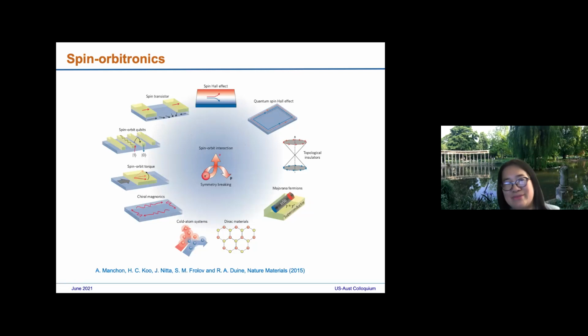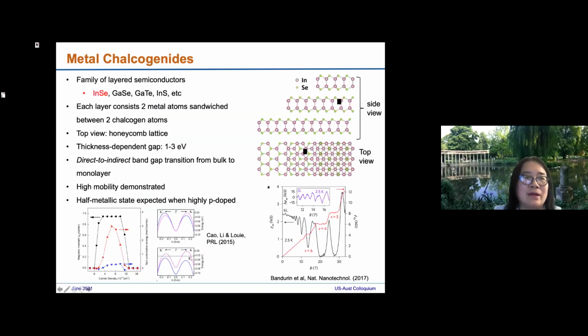But there's also a love-hate relationship between researchers and spin-orbit coupling, because on the one hand it can give us all these great phenomena and devices, but on the other hand it also creates extra scattering. A lot of times it reduces the carrier mobility and, for example, the spin diffusion length. So we're pretty excited because in 2D layered devices, the spin-orbit coupling is very tunable. In principle, in places where you want spin-orbit coupling, you can make it large, and in places where you don't, you can make it small, even go to zero entirely.